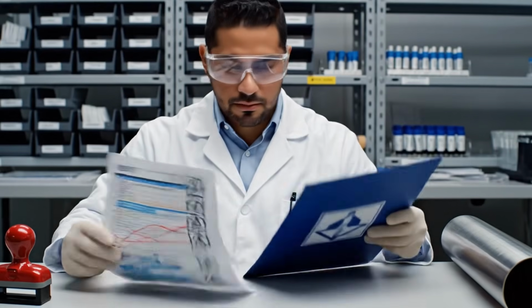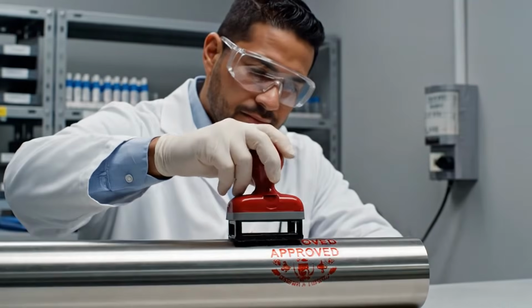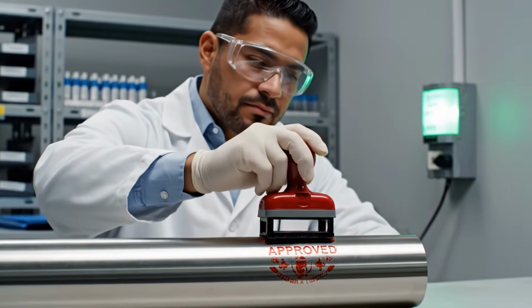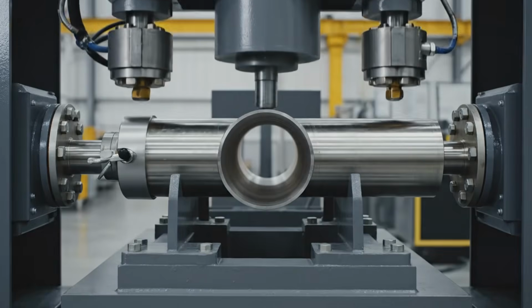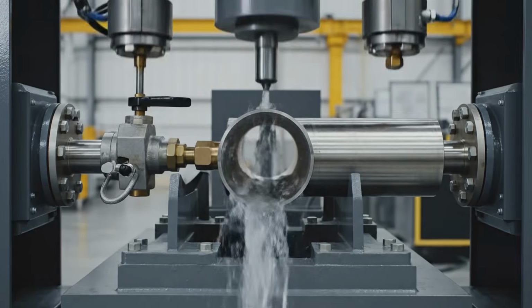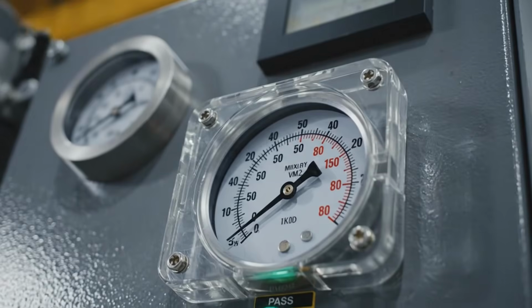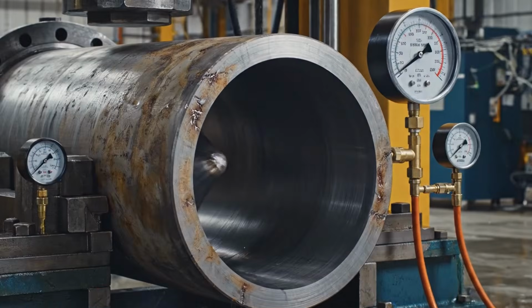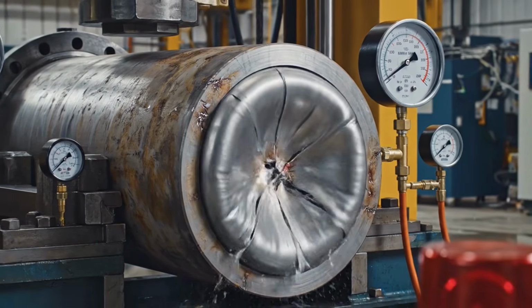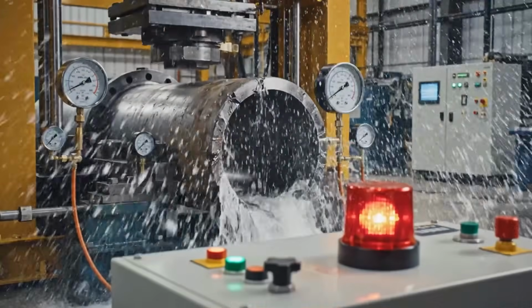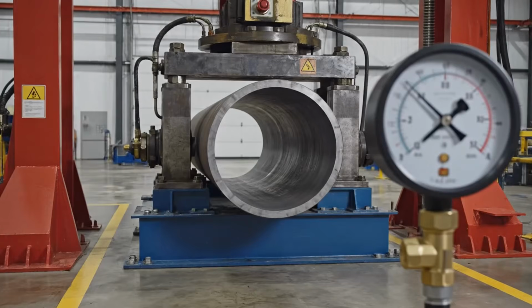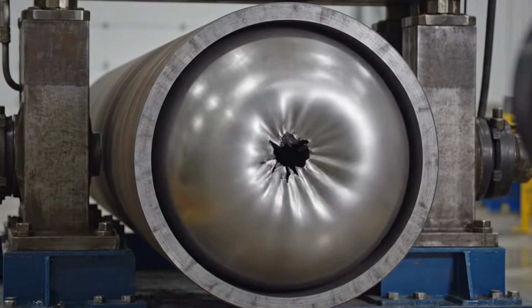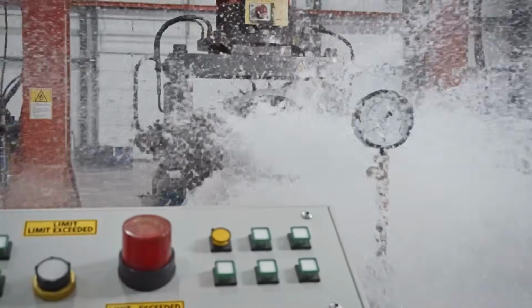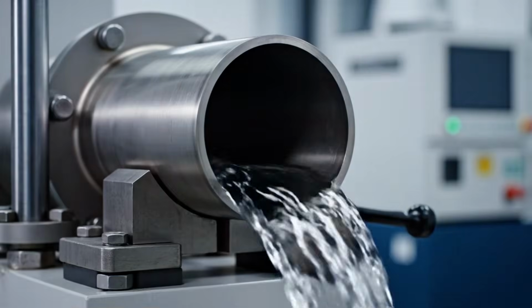An emblematic test is the hydrostatic test. The tube is sealed at both ends, filled with water, and pressurized above the intended service pressure within normative parameters. If a weak point, a leak, or an abnormal deformation exists, the piece fails. Water is used because, unlike a gas, it stores much less compressible energy and makes the test safer. The important thing is not only to see if it bursts, but to verify that it withstands the pressure without leaks or irregular behavior.